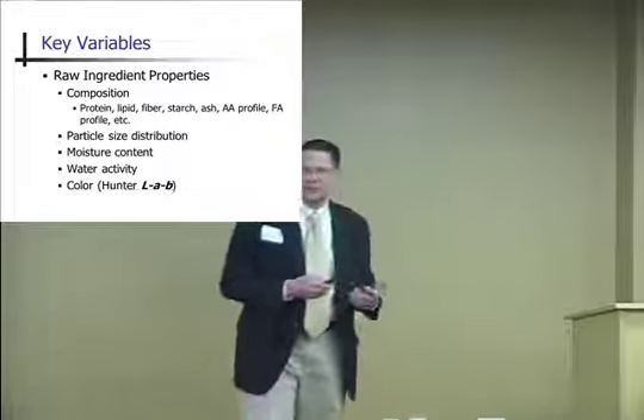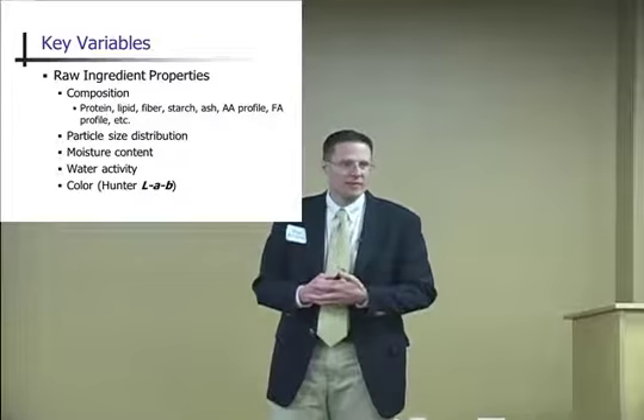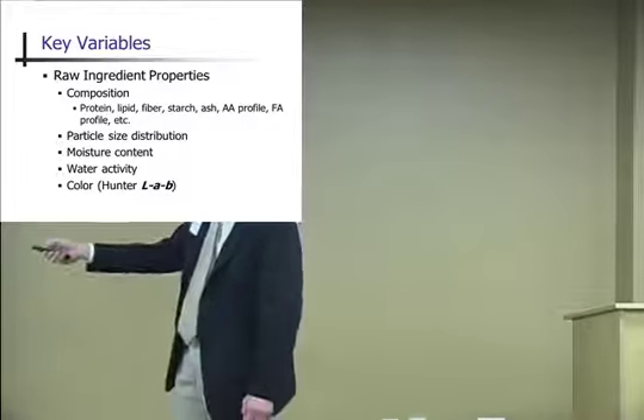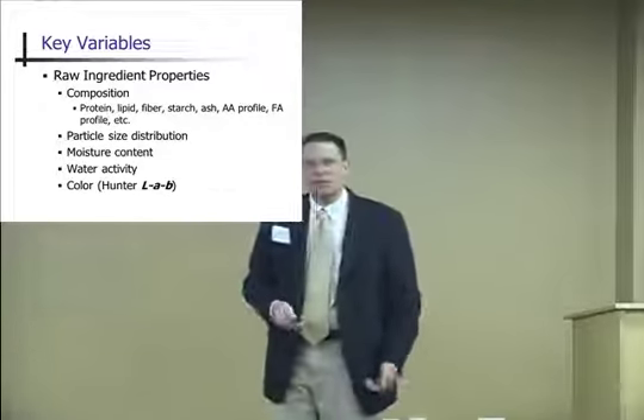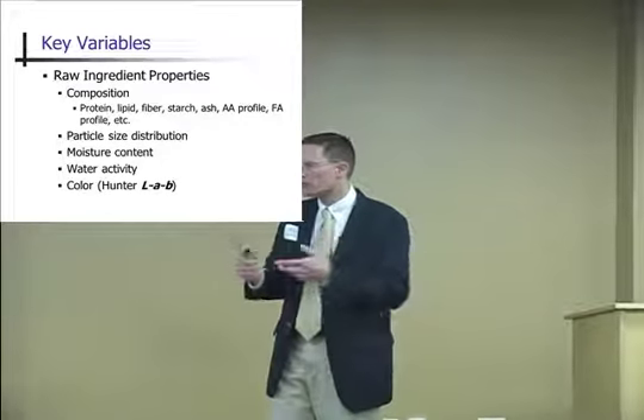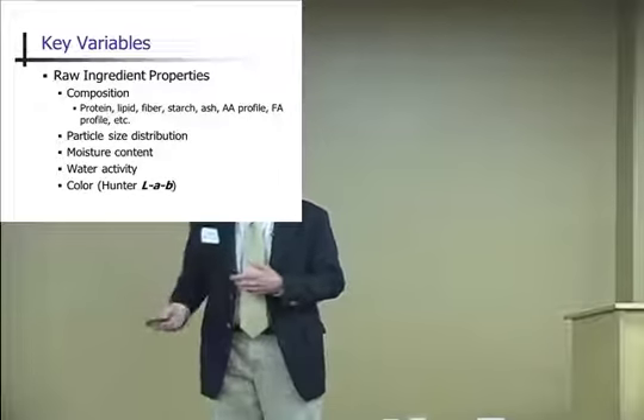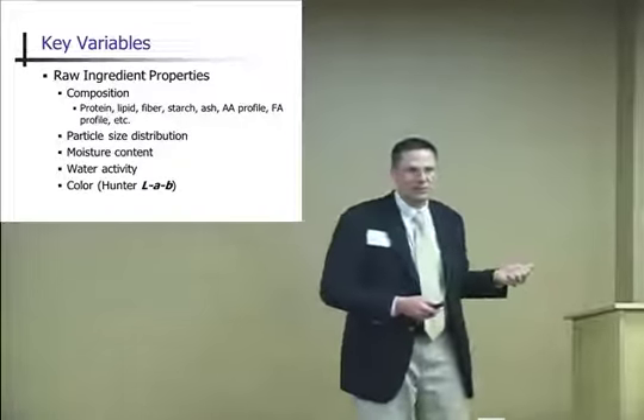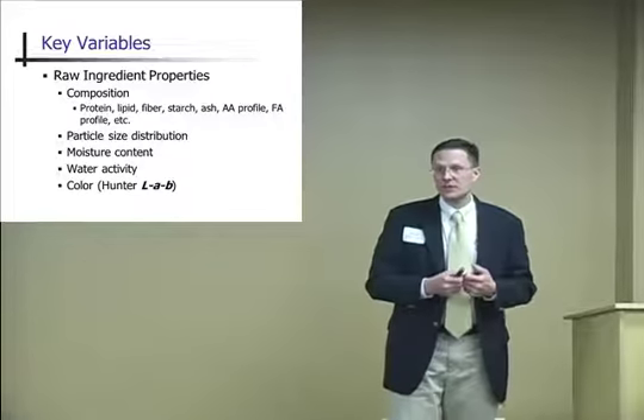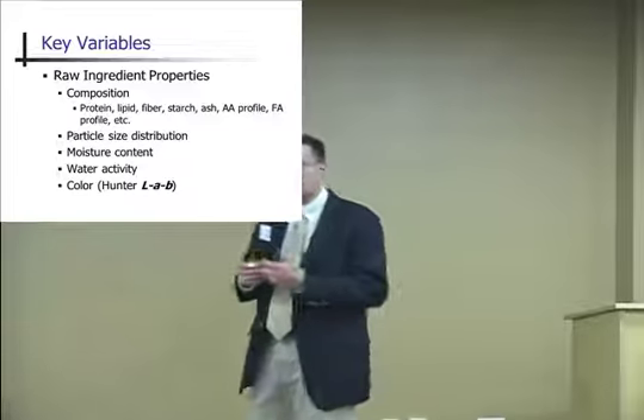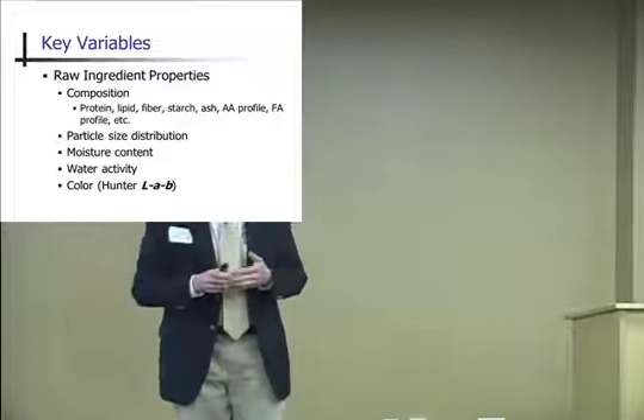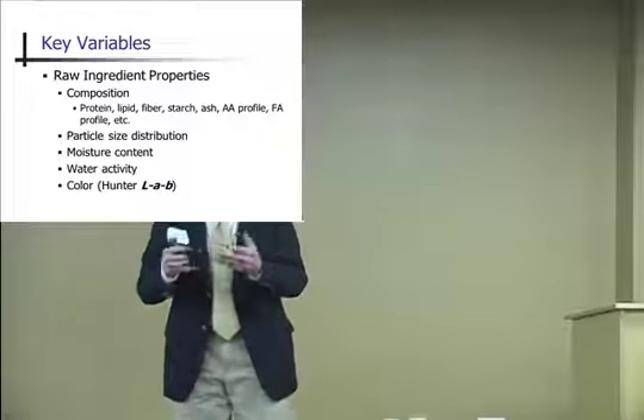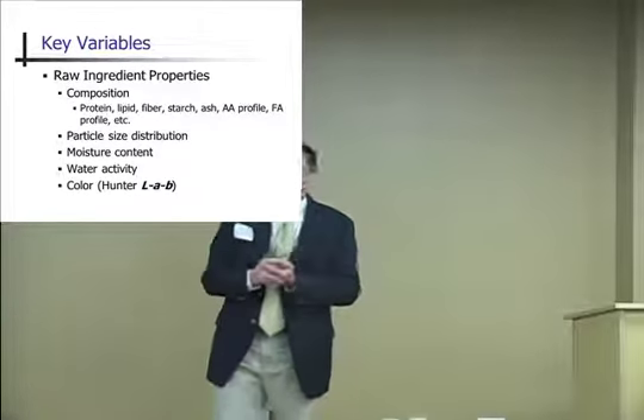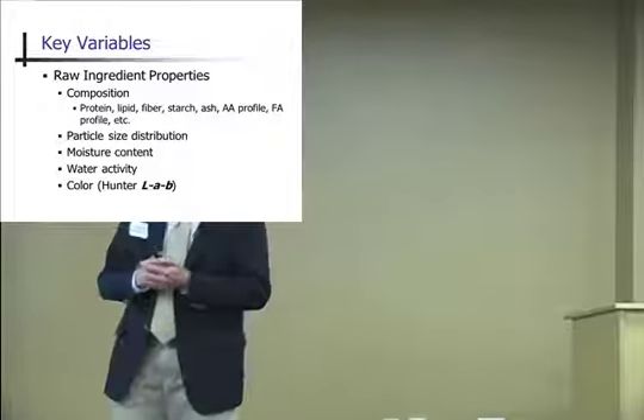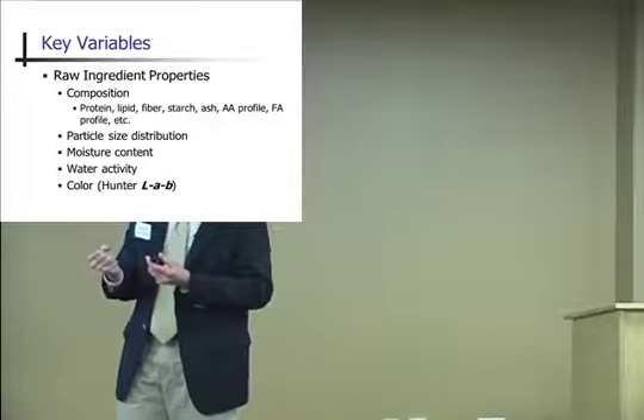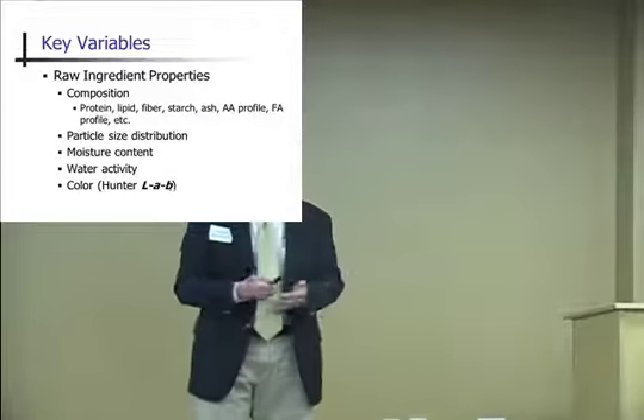So when we think about our raw ingredient properties, okay, of course, amino acids, fatty acids, protein, fat, fiber, ash, the whole compositional aspect. Okay, we also need to think about particle size distribution, because when you are blending a feed, if you're using DDG or using soybean meal or soy protein concentrate, those ingredients are going to have different particle sizes. And when you put them together in a mixer, you move those blends out of the mixer, you're going to have particle segregation. So you're going to have concentrations, or you might have, let's say you have some of the soy protein concentrate or soy protein isolate. That stuff absorbs water, so it tends to clump.